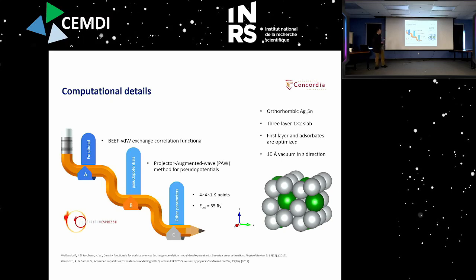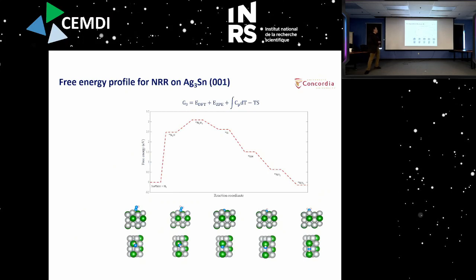Right. And so we use the Quantum ESPRESSO program for these calculations. OK, so here is a free energy profile that we characterized for the NRR on this type of alloy, silver tin. And so you can see that we have a high barrier for adsorption of the first intermediate step. So this is the N2H adduct.